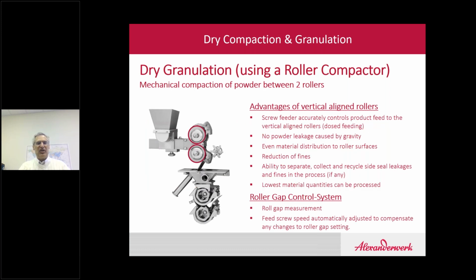The Alexanderwerk machines actually have vertically aligned rolls and a horizontal feed screw. There are some distinct advantages to this technology because we use our feed screw more as a metering screw. We're actually removing the effects of gravity. So when you're processing a large batch, and in the beginning, if you're feeding with an IBC, for example, you may have, say, 3 or 4 or 5 feet of head height of material over your feed screw. By using a horizontal feed screw, it takes away the effect of gravity. So we don't want to see a higher pre-compression at the beginning of the batch versus the end. So for that reason, our technology using the horizontal feed screw is very favorable.